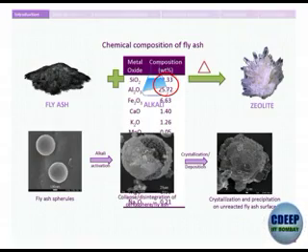Fly ash should not be seen as a perfectly good material, or a magic material or anything. So it should also be tested to determine whether it has any potentially hazardous elements present in it, any heavy metal present in the sample or not. So we can wash it with distilled water, deionized water, and see if there is any kind of heavy metal leaching out of that sample, and then we can run an ICP analysis to check whether the fly ash is okay or not. Because suppose we use it as a fill material, we don't want it to leach out heavy metals into the groundwater table, right? Plus, sir talked about the acid mine drainage, and sometimes fly ash is also used to close the mines. The mines that you excavate, you dump this fly ash back into those mines. Even then, you have to check whether the fly ash is a potentially harmful source, or whether it is an inactive or inert material.